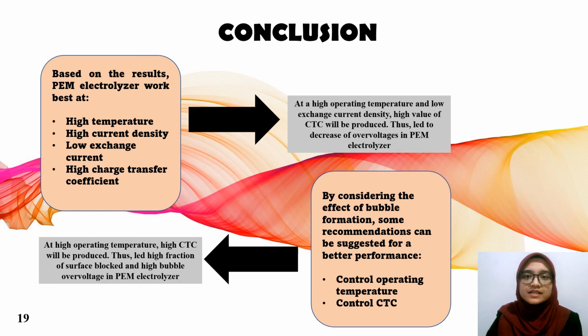From the results, it can be concluded that the PEM electrolyzer works best at high temperature, high current density, low exchange current density, and high charge transfer coefficient. This is because at a high operating temperature and low exchange current density, a high value of CTC will be produced. Thus, it will lead to a decrease of overvoltage in the PEM electrolyzer.